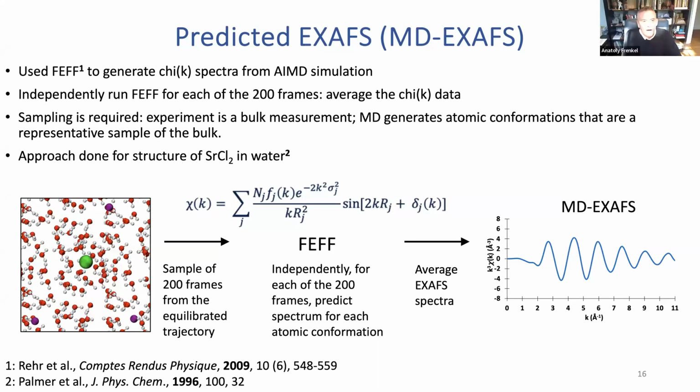I think you used pair contributions or multiple scattering contributions, all contributions obtained for a snapshot as your simulation obtains, right? That you did not have to include any sigma square or coordination number because you could use the atom by atom calculations. Is that what you did?